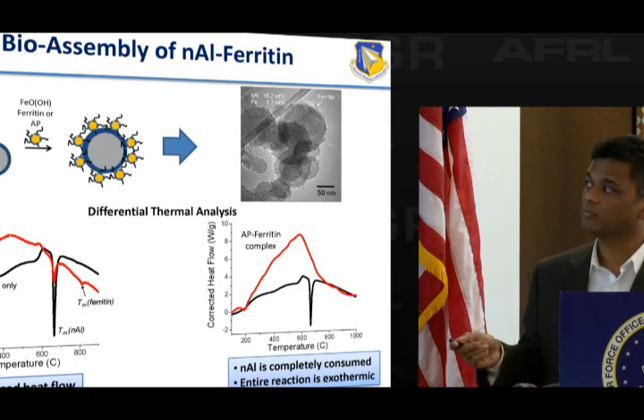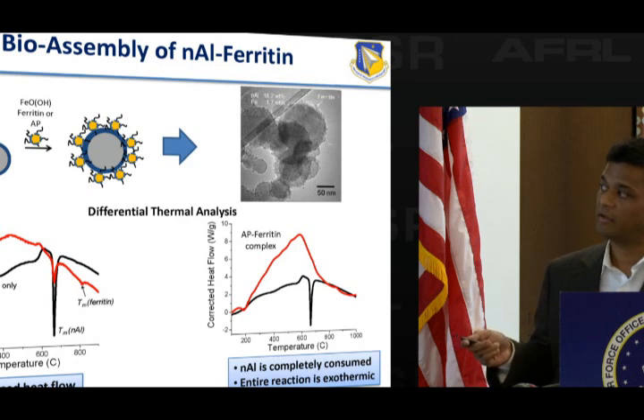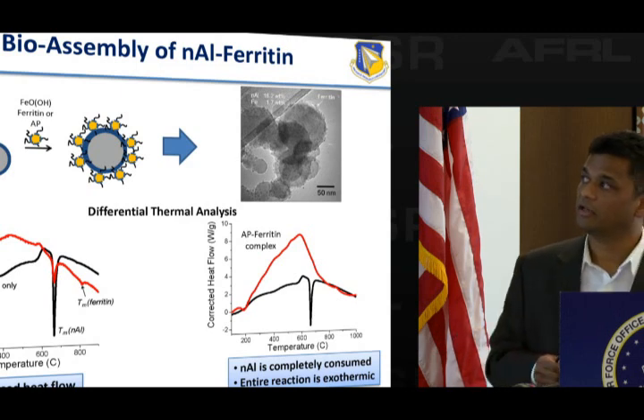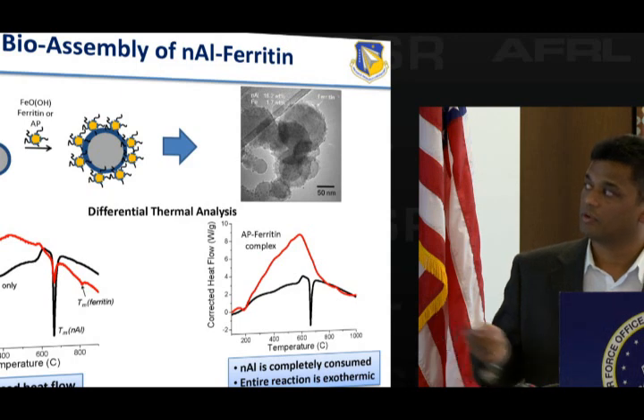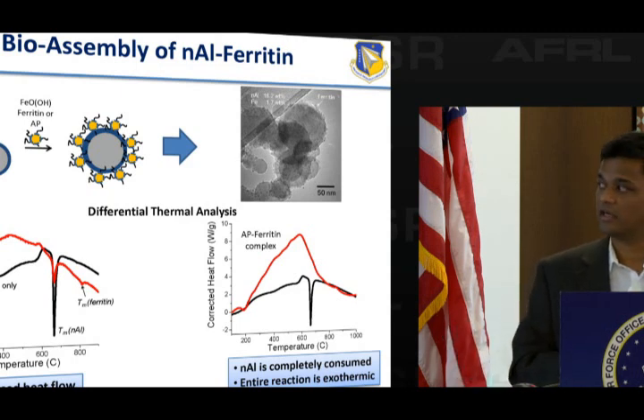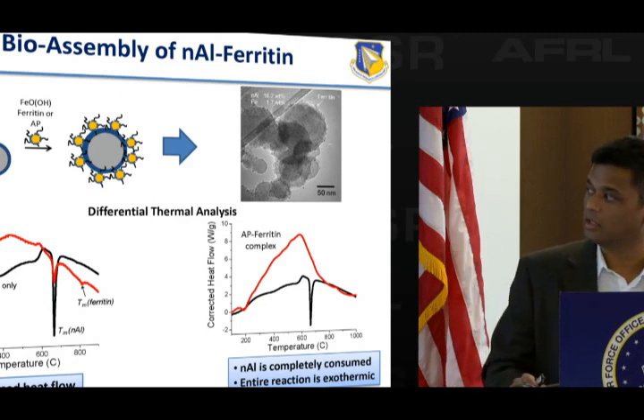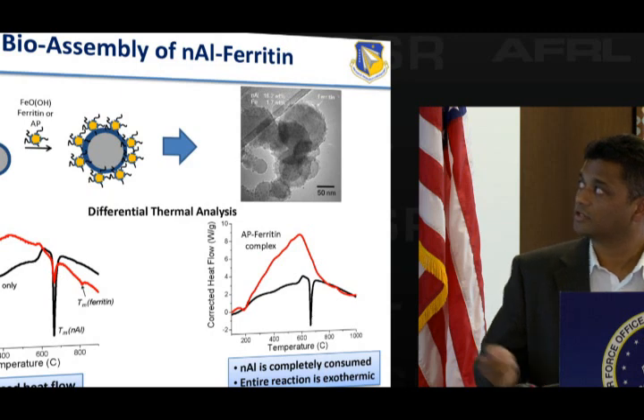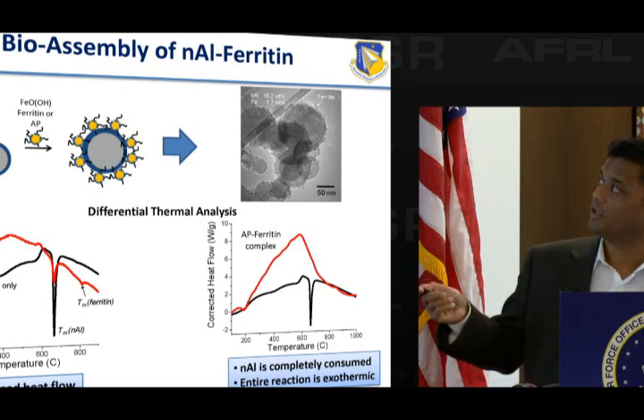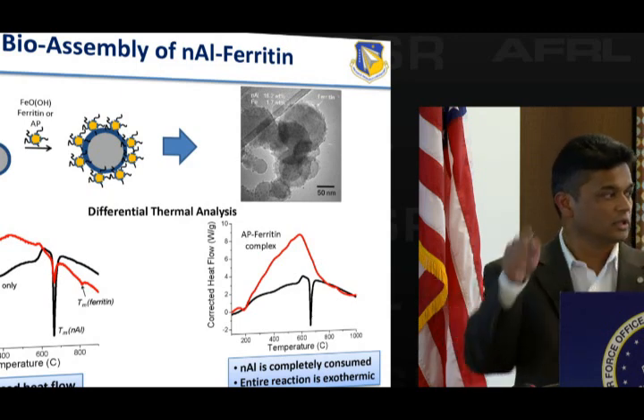Because you have the thermite reaction, but you also bring in the oxidizer ammonium perchlorate, which you can also load onto the surface of the ferritin cages. And the reaction is entirely exothermic. You can see that huge burst in the heat flow as you do the reaction. This is a TEM micrograph showing the aluminum nanoparticles, and you can see the ferritin is small. This is unstained, so the electron-dense dots that you see there are actually the iron oxide from the ferritin that decorates the surface.